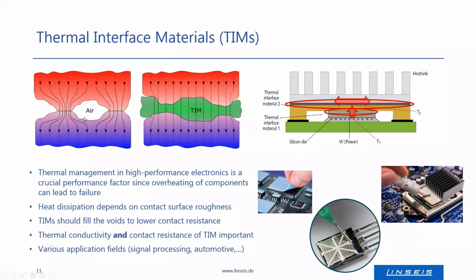And here come now the thermal interface materials. The thermal interface material should fill these voids, and by that it establishes a larger contact area and enables a maximum thermal conduction with a low thermal contact resistance. So thus, the aim is to improve the thermal contact between the heat source and the cooler in order to get rid of the waste heat. So the pressure and temperature dependent thermal impedance are of interest, as well as the stability of these materials during thermal or mechanical cycles.